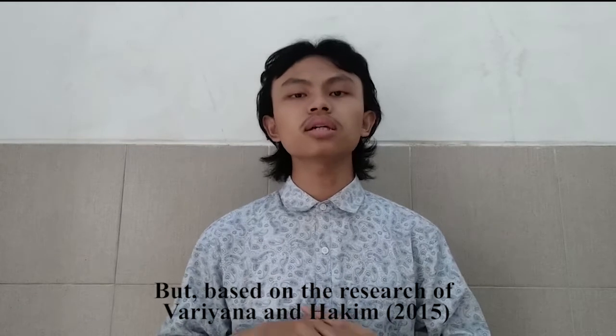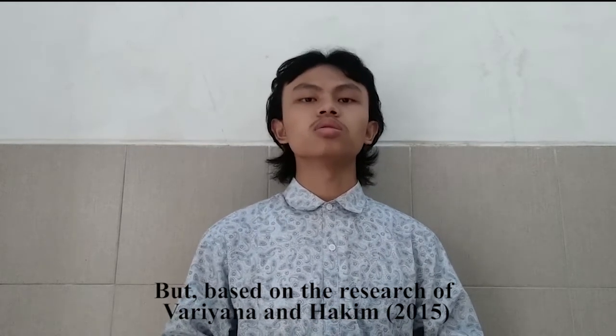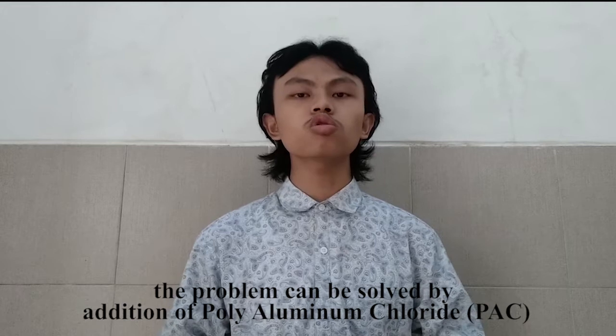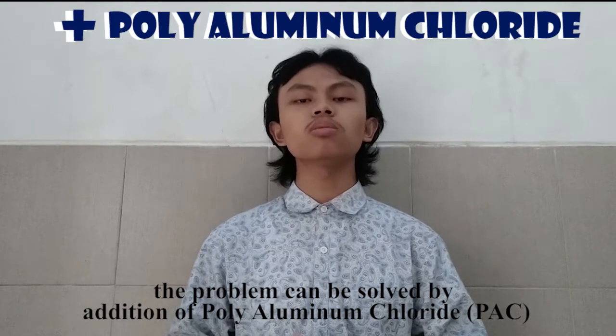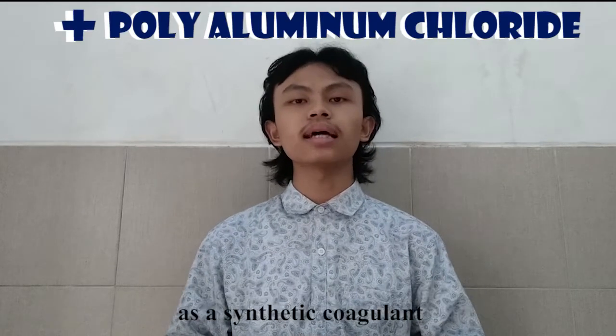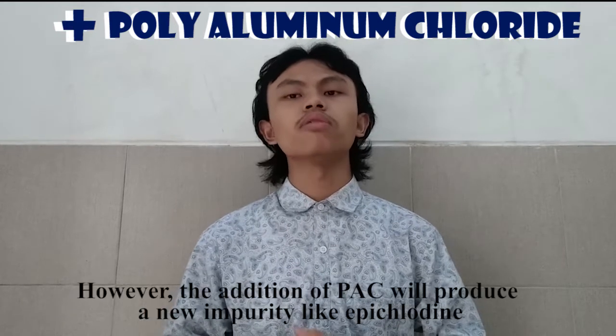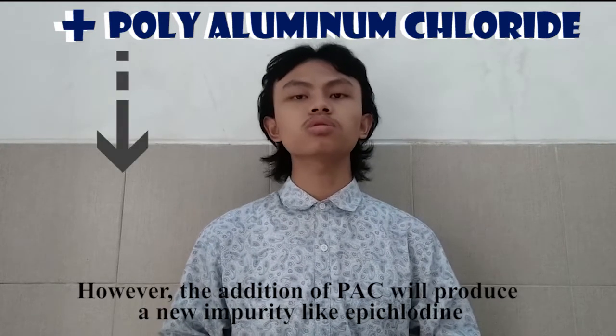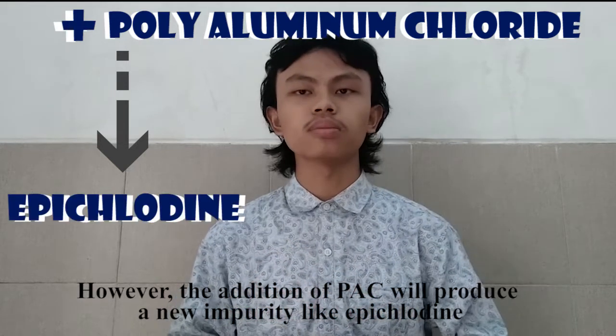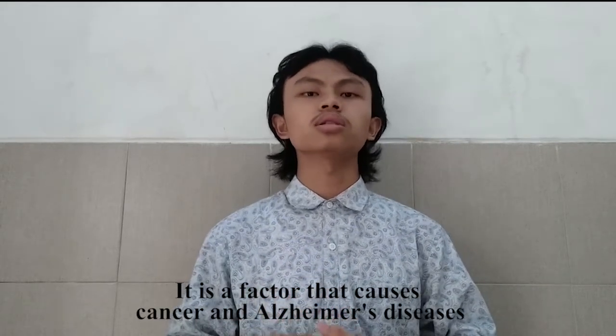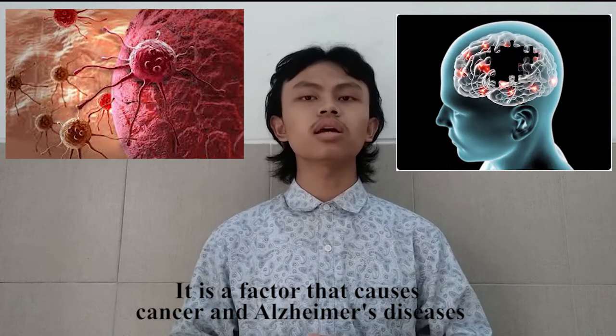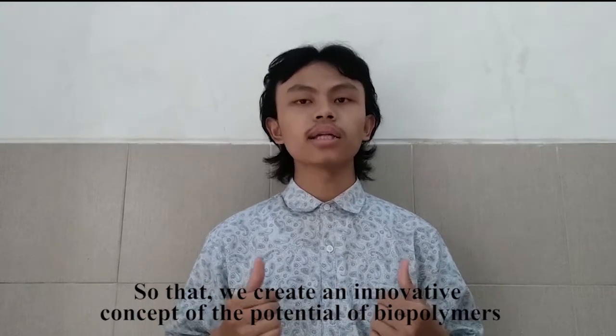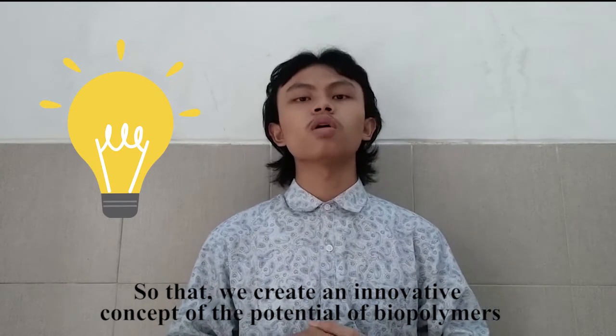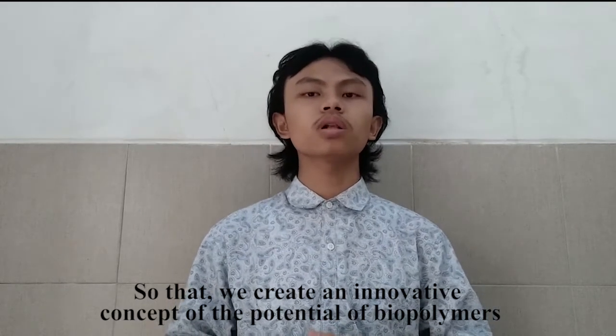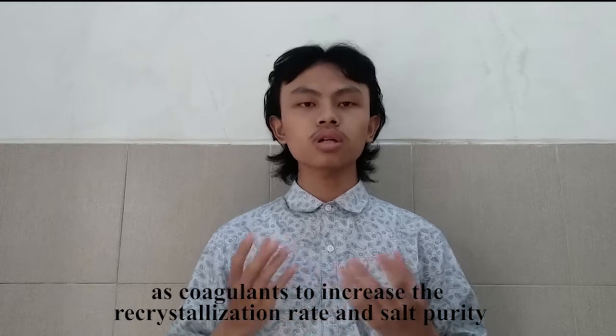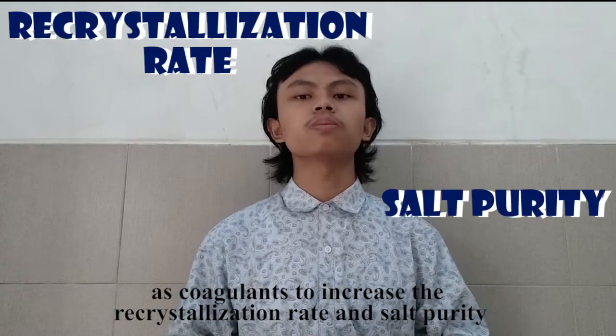But based on the research of Variyana and Hakim in 2015, the problem can be solved by the addition of polyaluminum chloride, or PAC, as a synthetic coagulant. However, the addition of PAC will produce a new impurity like epichlorohydrin. It is a factor that causes cancer and Alzheimer's disease if consumed continuously, so we created an innovative concept of the potential of biopolymers as coagulants to increase the recrystallization rate and salt purity.